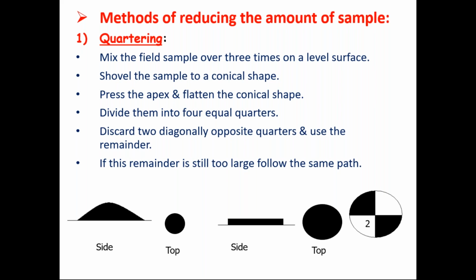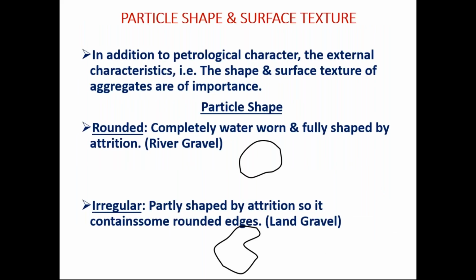Mix the field sample over 3 times on a level surface, shovel the sample into a conical shape, press the apex and flatten the conical shape, divide it into 4 equal parts, discard two diagonally opposite quarters and use the remainder. If this remainder is too large, follow the same process once again. So this is how the sampling of aggregate is done for sampling purposes.